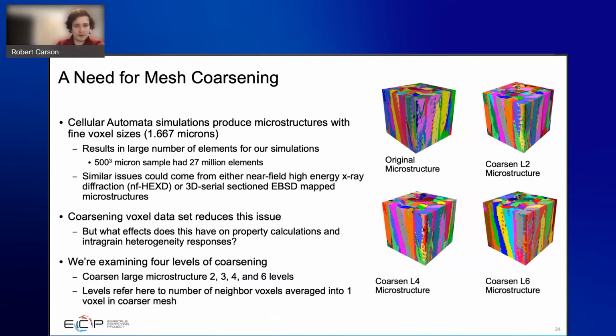So I took our original microstructure and coarsened it at several different levels. The levels I looked at were 2, 3, 4, and 6 levels of coarsening. Levels here refer to the number of neighboring voxel grains that were averaged into one voxel in the coarser mesh. What we can see is that by doing that averaging between the original and the coarser, we lose a lot of the finer details, but we still retain the major columnar grains that we see.